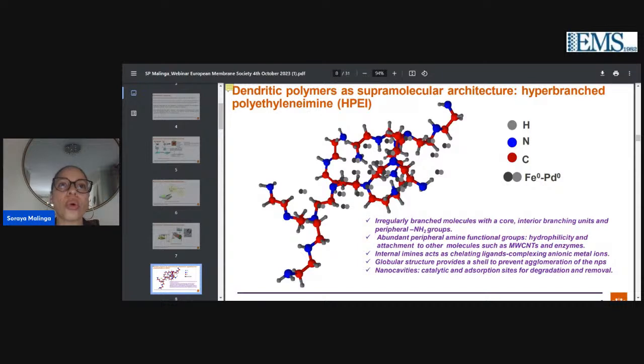We have also used it to attach other molecules, such as multi-wall carbon nanotubes, as well as enzymes, on this hyperbranched polymer, because we're taking advantage of the NH2 groups, which are quite easy to functionalize. We also have internal imines within the structure that can act as chelating ligands, because, as I mentioned before, we are interested in preparing nanoparticles that can have catalytic and photocatalytic properties induced within the membrane. What these imines do is chelate the metals that you're trying to reduce to nanoparticles. They can also chelate heavy metals, so if you are interested in removing heavy metals from water, they're an added advantage.